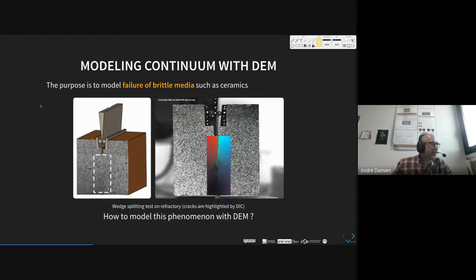So here I have an example of an experiment which is called the wedge splitting test. You have a block of ceramics, a typical refractory, and the wedge here is moving down to open up the sample and make a controlled fracture experiment. So this is a method to measure the tenacity of ceramic material. So how to model this experiment with DEM?